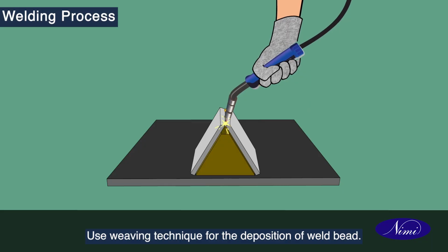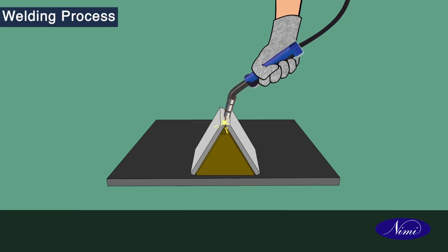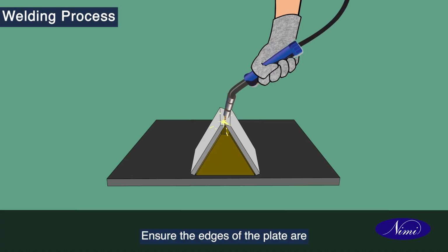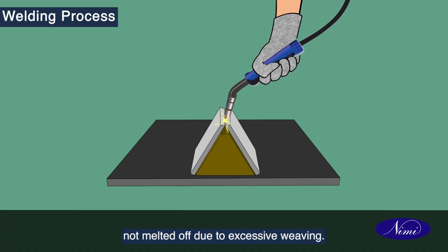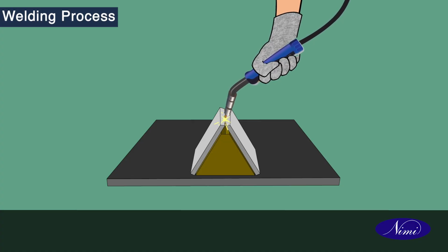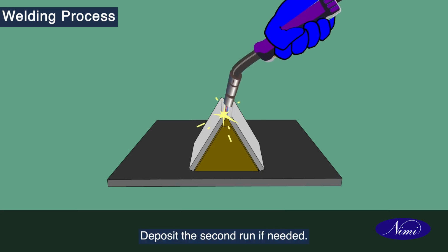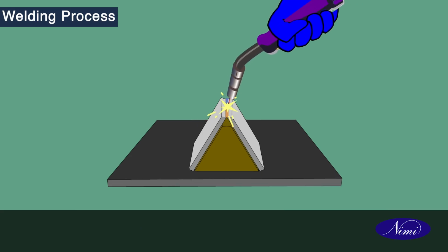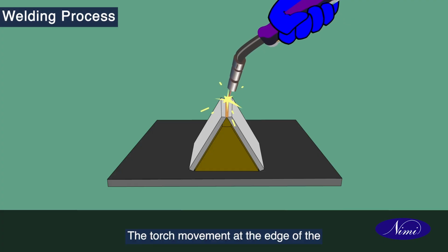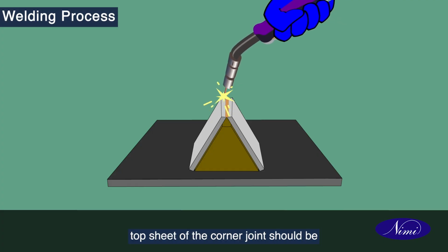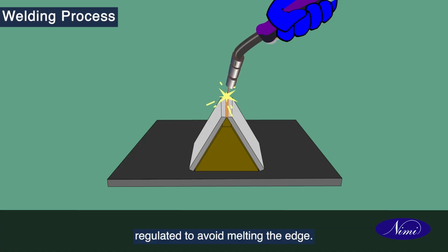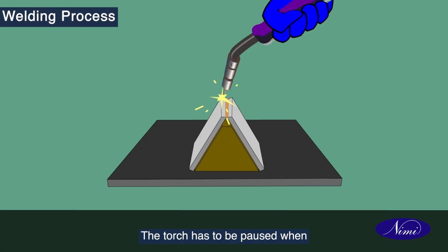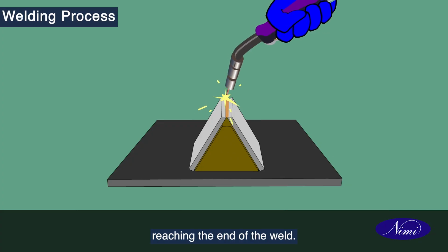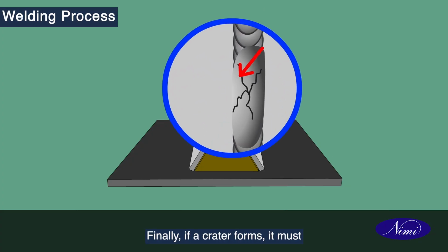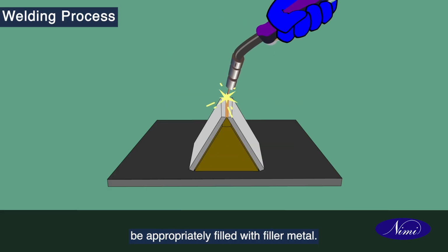Use weaving technique for the deposition of weld bead. Ensure the edges of the plate are not melted off due to excessive weaving. Deposit the second run if needed. The torch movement at the edge of the top sheet of the corner joint should be regulated to avoid melting the edge. The torch has to be paused when reaching the end of the weld. Finally, if a crater forms, it must be appropriately filled with filler metal.